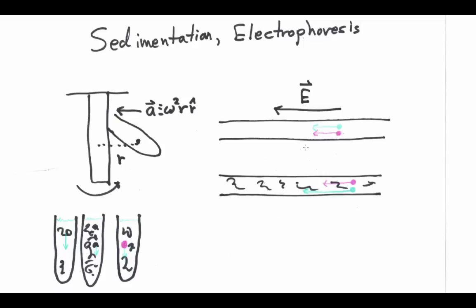If you try applying this technique to DNA fragments, you have a little problem. In plain solvent, the DNA fragments decline to separate. One solution is to replace the innards of this capillary, which is filled with water. We'll replace this and we'll fill the innards of the capillary with cross-linked gel. Or we'll just use the cross-linked gel itself as a separatory matrix. And that actually works, except making really uniform gels turns out to be experimentally tricky. There is, however, a third solution.